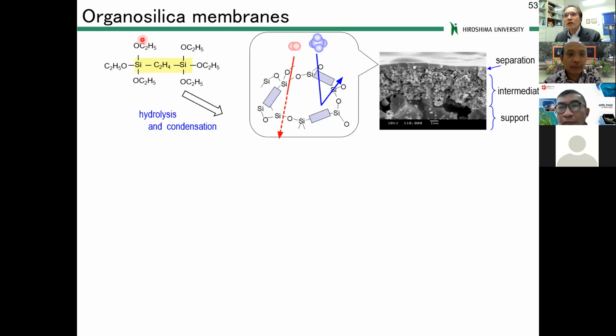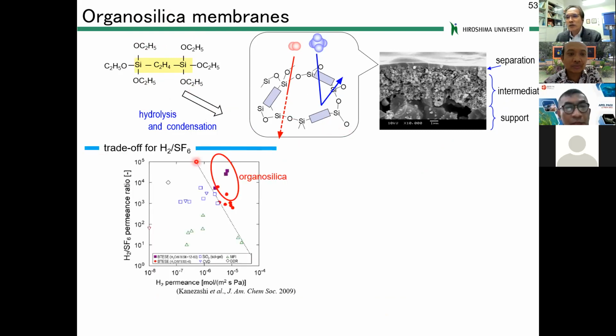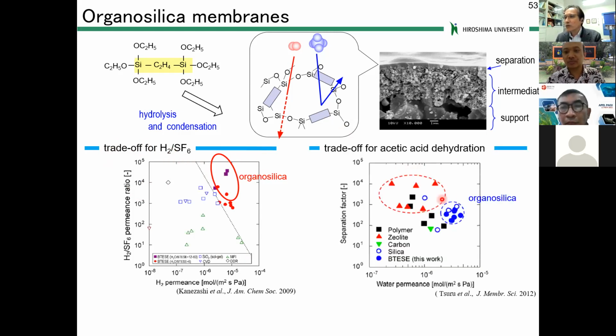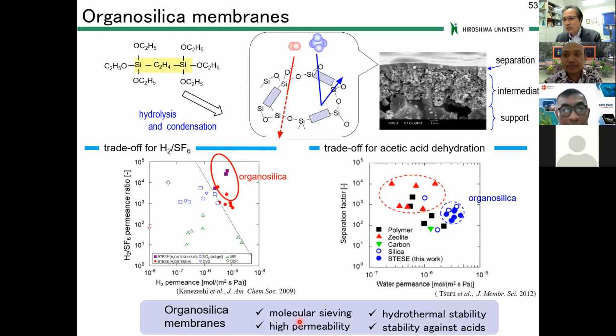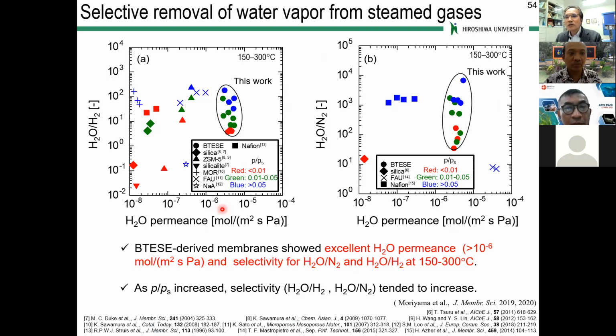Okay, now move to a little bit different topic, steam recovery. Almost 1 hour, so I need to rush. Now organosilica membranes have this linking unit, which shows very high performance in hydrogen over SF6, and this membrane also shows a high performance for acetic acid dehydration. So organosilica membranes show high molecular sieving, high permeability, high hydrothermal stability, and are stable against acid. So we apply these membranes for steam recovery, the selective removal of water vapor from steam gas.